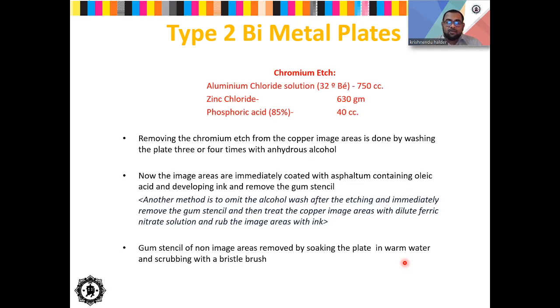These are the ingredients a plate maker must use in order to create a chromium etch. For the chromium etch, the plate maker uses 32-degree Baumé Aluminium Chloride solution, about 750 cc, along with 630 grams of zinc chloride, and 85% phosphoric acid, taken only about 40 cc. This is the chrome etch solution that has to be poured over the plate, and it will start etching the chromium from the image area.